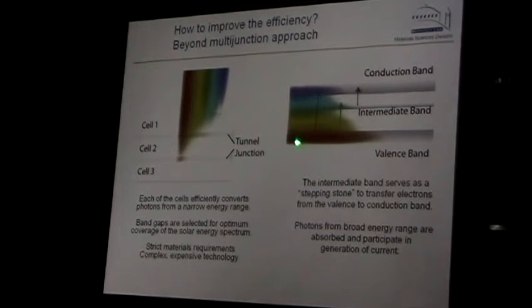So basically, in this case, you can absorb light of different energies with transitions between different states in the valence band, conduction band, and the intermediate band. This increases the total amount of light absorbed, and the open circuit voltage, or performance, is determined by this large gap, because the intermediate band is isolated from the rest.